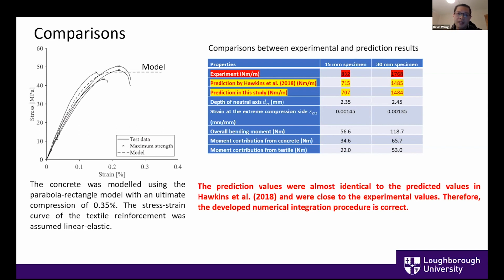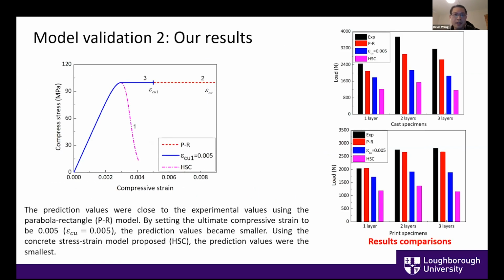So based on these comparisons, we can see our prediction values are almost identical to the predicted values in Hawkins 2018, and also close to the experimental values. So our numerical integration procedure is correct. And then we did our model validation for our own test results.